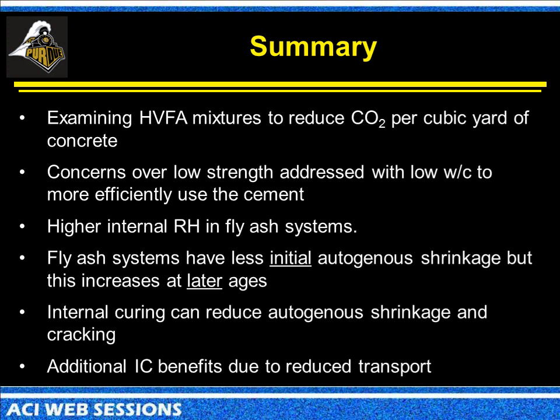Fly ash systems will have less initial autogenous shrinkage, but the rate of autogenous shrinkage that picks up is going to increase at later ages. So you may think, oh, well, we're out of the problem because we've gotten to 5 days and we haven't seen cracking. But remember, fly ash has more chemical shrinkage. It's taking place later in time, so we really need to be focused on what's happening at slightly later ages.